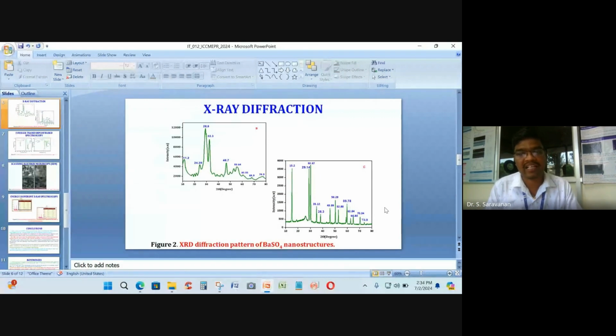So first you can see the X-ray diffraction. This first is showing the ethanol-based XRD. Next is showing the DI water-based XRD. You can see the structural properties. DI water shows more intense and sharp diffraction peaks. However, ethanol shows slightly broader diffraction peaks, and the peaks around 24.39, 28.9, 32.3, 46.7 are all well matched with the JCPDS files. So it is confirming that barium sulfate is present.